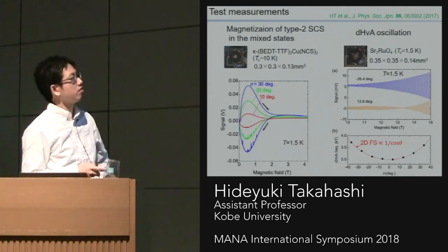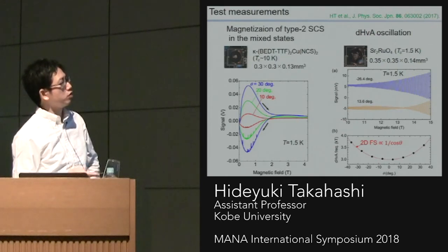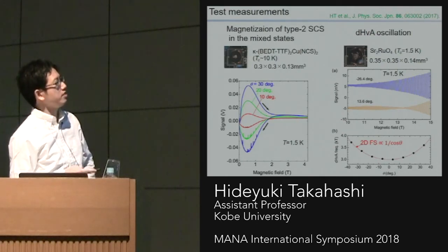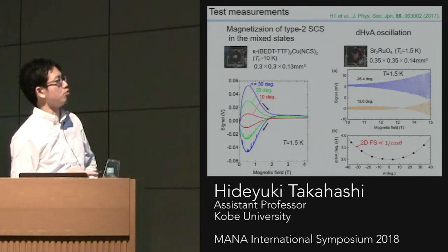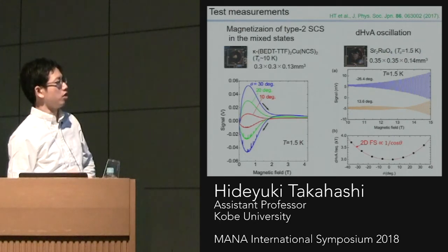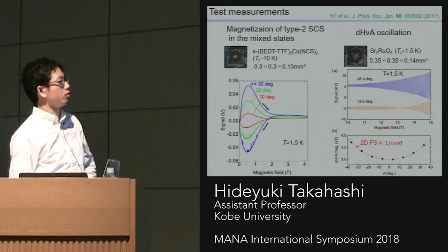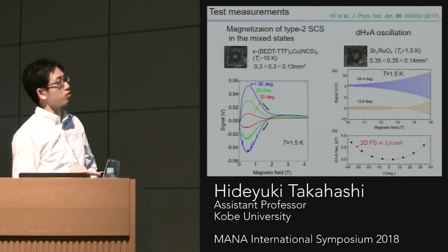superconductors. And the right figure shows the quantum oscillation effect of strontium ruthenate. This is also a layered superconductor, but at this temperature, this sample is still in the normal state. This oscillation period corresponds to the k-space property of the sample. And by extracting the oscillation frequency as a function of the angle between the C-axis and field direction, we can know the shape of the Fermi surface. The data is well fitted by an ideal case for a 2-dimensional substance. So this is consistent with this being a layered superconductor.